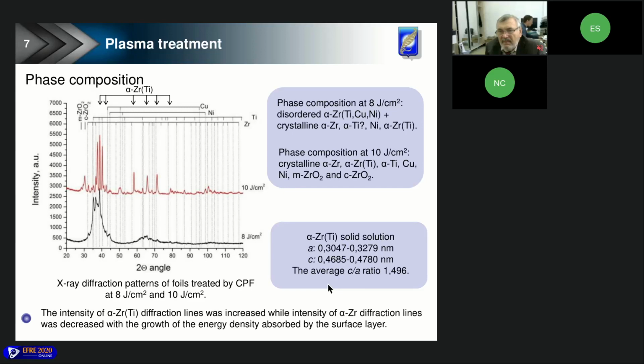The general appearance of zirconium oxide in the surface layer could be explained by interaction of residual atmospheric gases, in particular oxygen, with atoms of the surface. As a result of such interaction, a surface oxide with a thickness of a few tenths of a nanometer grew on the surface.